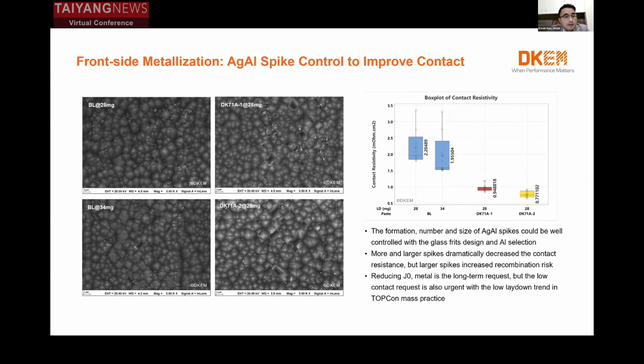The left part of the SEM is the baseline paste, and you can see that there are fewer imprints. The imprint means the original locations of the silver aluminum spikes. After we adjusted our glass system and also optimized our aluminum selection with DK71A aluminum silver paste, you can see that there are lots of spikes that give us a great benefit on the contact resistivity. But we have to pay attention that too big size of spikes will cause a high J0,metal, a loss of metallization recombination. As we all know, reducing J0,metal is a long-term request for TOPCon front-side metallization.